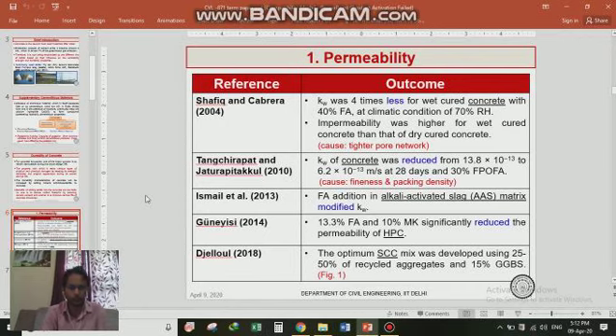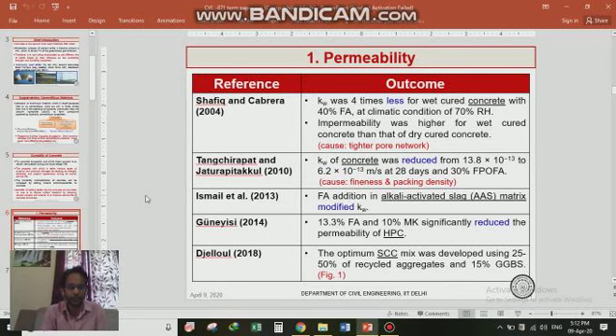In 2010, Tangchirapat and Jaturapitakkul studied the influence of fine palm oil fuel ash in concrete, and concluded that the permeability coefficient of concrete with 30% FPOFA was reduced from 13.8 into 10 to the power minus 13 to 6.2 into 10 to the power minus 13. Almost a 50% reduction took place at 28 days, and the major cause was fineness, as the fineness of FPOFA was much higher. Therefore, the packing density within the matrix was improved, which caused the impermeability.